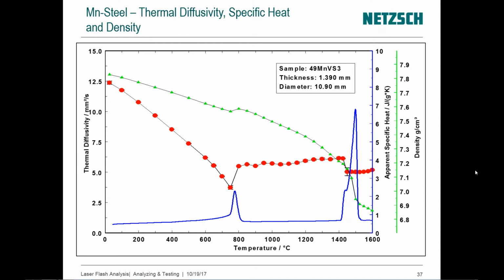The reason why is because we always measure a signal relative to a prior state. So we have steady state, the detector signal is at a level, and then we introduce the short pulse, and that signal increases. We know there will be a temperature increase, and there will be a change in radiated energy from the surface, and a change in the detector signal accordingly. But the change in temperature is so small, far less than 10 degrees, that we can assume that the signal from the detector is proportional to the temperature change of the surface. So proportionality is assured there, and that's not a problem.